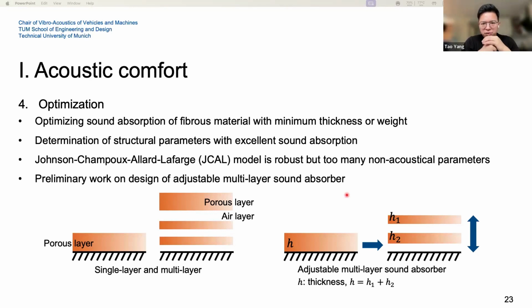So the motivation is to optimize the sound absorption of fiber material, and of course, it should be able to determine the structure parameters and then use the structure parameters to design the specimen to carry out the measurement. The Johnson-Champoux-Allard-Lafarge model is more robust compared to other empirical models, for example, the Miki model. But it has too many non-acoustic parameters. In my current work, I use a multi-layer structure, in which the porous layer and the air layer are alternately arranged. It means the sound wave comes to the top, the first layer is a porous layer, the second layer is an air layer, and it continually repeats.